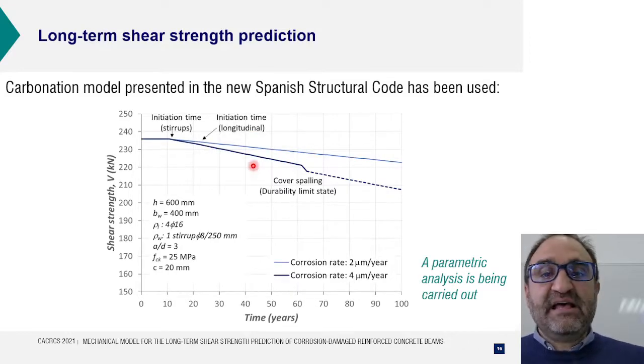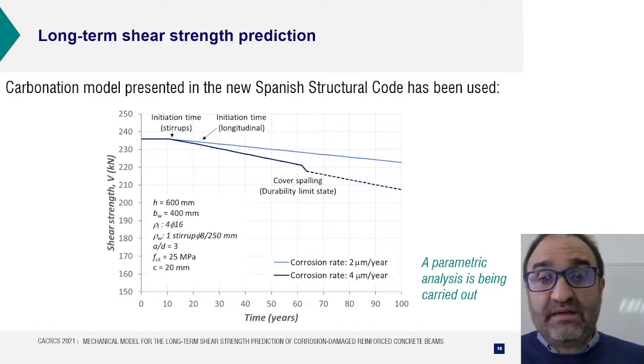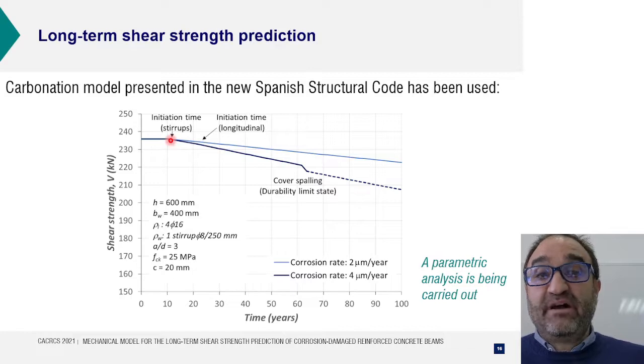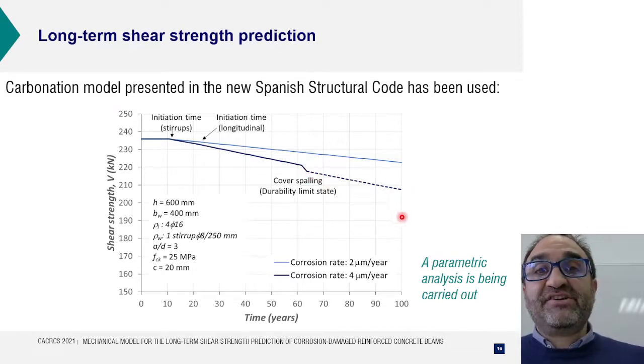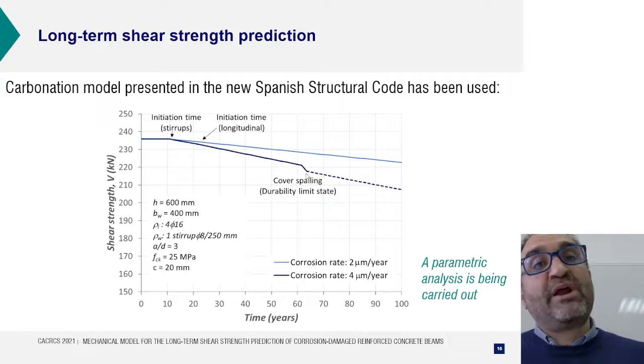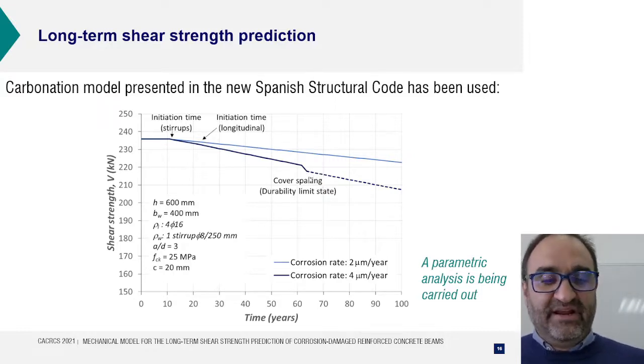And here, for instance, you can have a beam that you were thinking of in one exposure class, but it was wrong. And then for an already built beam, we can consider different corrosion rates. You can see here 2 micrometers per year or 4 micrometers per year. In this case, at 60 years, the model is predicting the cover spalling. And after this, you can see this dashed line, of course, the degradation will be higher because the corrosion rate will increase. We are still not considering this scenario. We get until here.